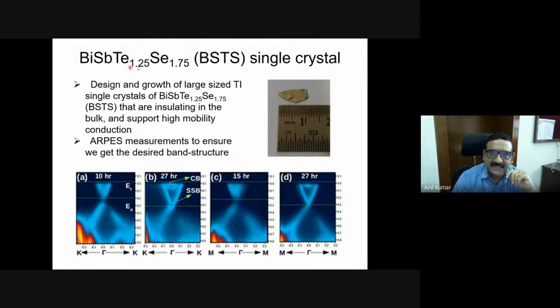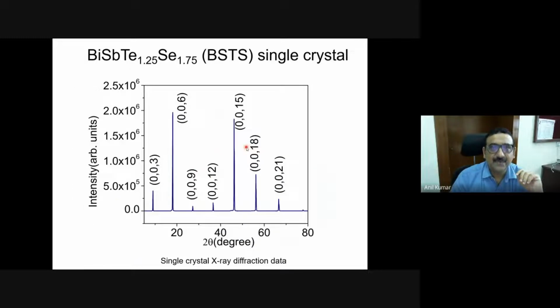For such a single crystal, if I look at the angle-resolved photoemission, you see that I don't see the bulk conduction band or the valence band here. I'm only seeing the surface state, and the Fermi level is within that band gap. So now I have formed the required crystal where the Fermi level lies within the band gap. If I tell you about the X-ray diffraction of these crystals, you will see 003, 006, 009, 012, 015, 018, 021 peaks. That means it's a 00L peak series, so it's a complete two-dimensional material with the c-axis oriented.